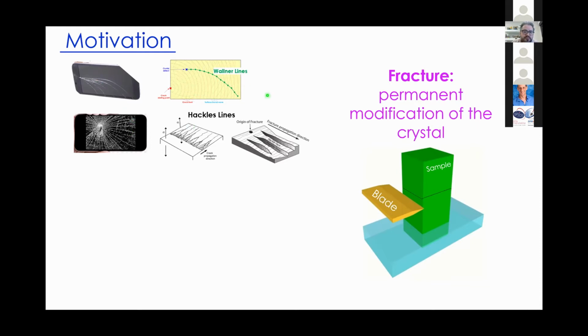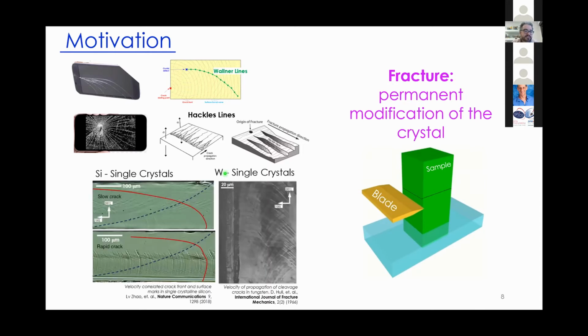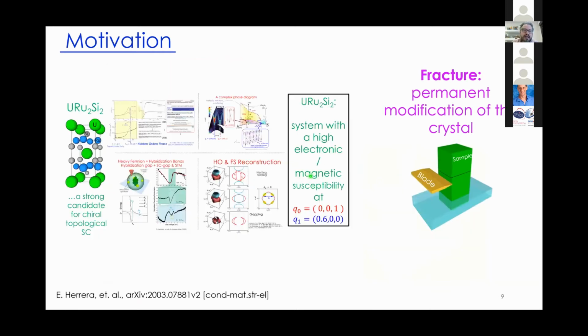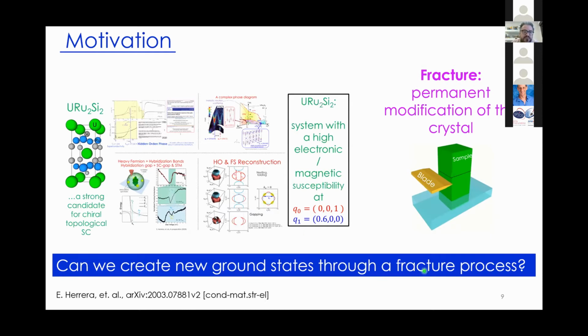These modifications can be due to the acoustic waves that are emitted when the crack front crosses defects during the cleaving process, or due to other local interactions of the crack front and the crystalline lattice, even when the crack front changes direction between consecutive layers of the solid. These effects have been studied in materials such as silicon or tungsten. Knowing that fracture produces permanent modifications on crystals, and having this kind of exotic system, the question we can ask is: can we create new ground states through a fracture process?